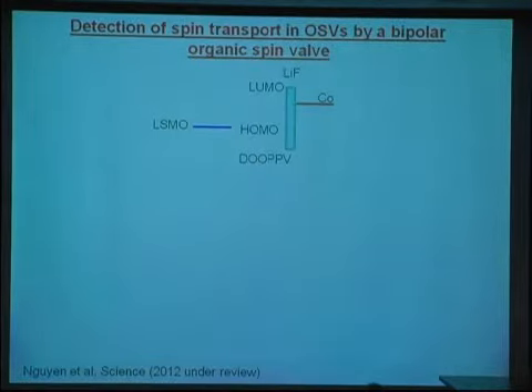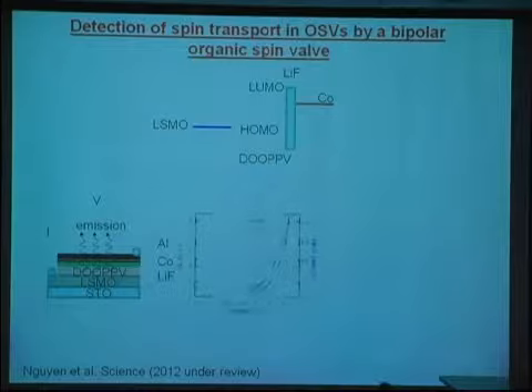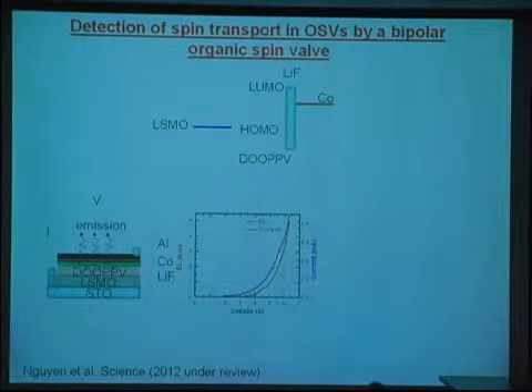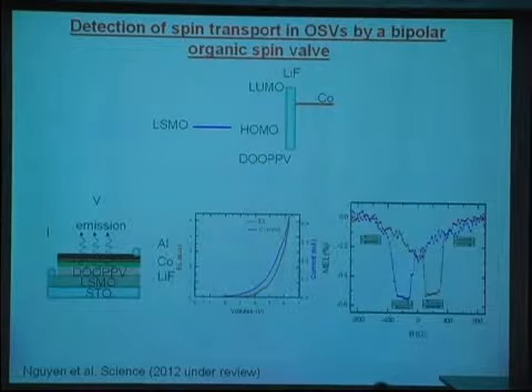Okay, so this is the device structure, and you can see that we get quite a good device based on the IV characteristics and also the electroluminescence versus voltage here. The turn-on of the electroluminescence is about 3 volts, which is very important. Because if the turn-on voltage here were 10 volts, it could be very bad because, like I told you, the spin injection capability goes down with the applied voltage. Okay, so this is the effect. Yes.